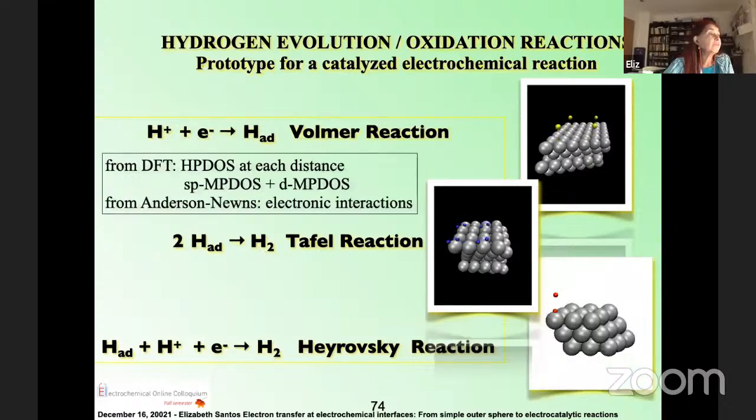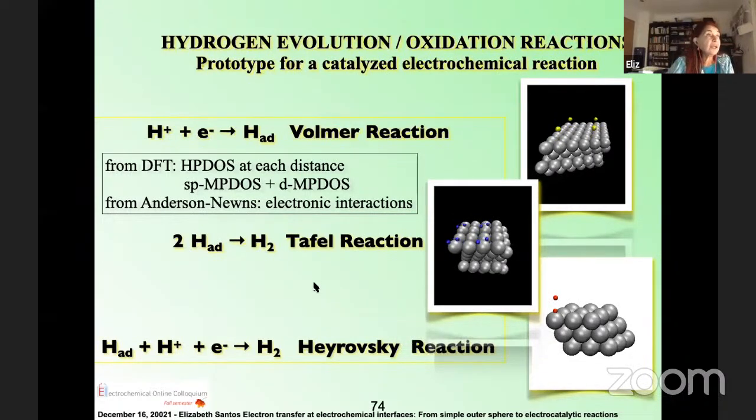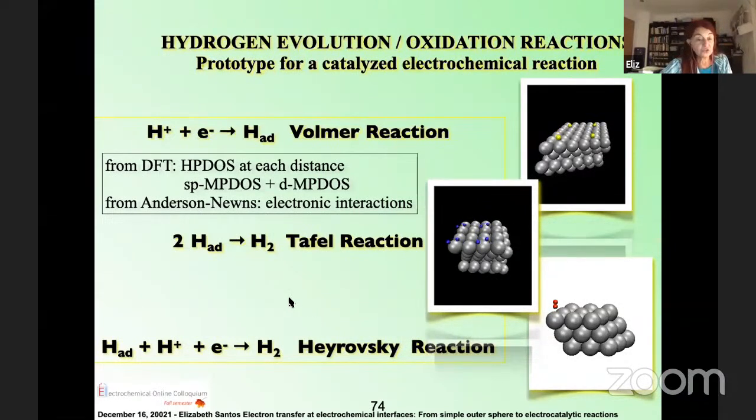And for the Heyrovsky step, we can calculate what happens when another hydrogen approaches an adsorbed hydrogen and forms the molecule. But these with DFT are all neutral systems. But anyway, this allows us to calculate how strong the interactions are between the electrode and the reactant.